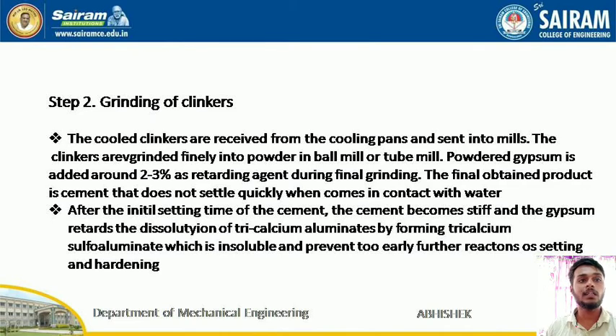After the initial setting time the cement becomes stiff, and the gypsum retards the dissolution of tricalcium aluminate by forming tricalcium sulfoaluminate, which is insoluble and prevents too early further reaction, that is, setting and hardening.